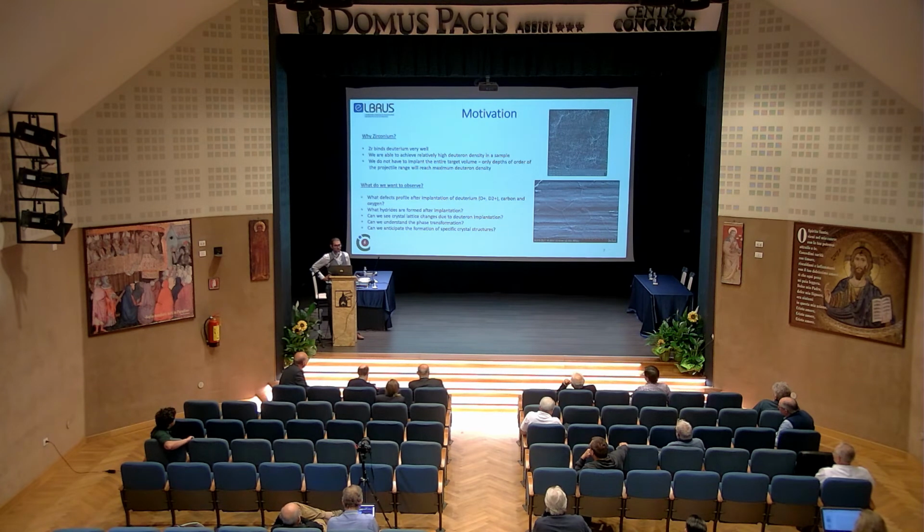Not a real crystalline structure? If you don't have a crystalline structure, well, we need other materials, of course. As Conrad was answering just before, we need to have a metallic structure, okay? That's very important because we need free electrons. These electrons are a necessary part of the screening energy enhancement, okay? Why we use zirconium is simply because zirconium binds to hydrogens, and deuteriums bind to zirconium and are stable. So in terms of experimental conditions, it's much easier than using palladium, because with palladium you implant hydrogen or deuterium inside, you stop the beam and everything goes away.